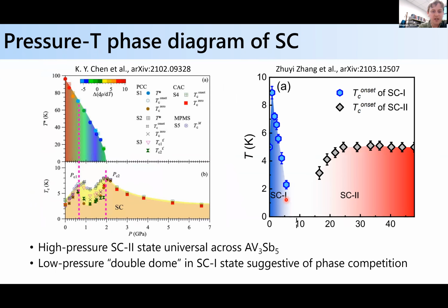And then the details even become more intricate as you look at that, which was the potassium system. You instead look at the cesium system and at details in this low pressure regime. This is some very nice work showing what they call a double superconducting dome. They start to suppress, sorry, this is the charge density wave state. They start to suppress the charge density wave state.